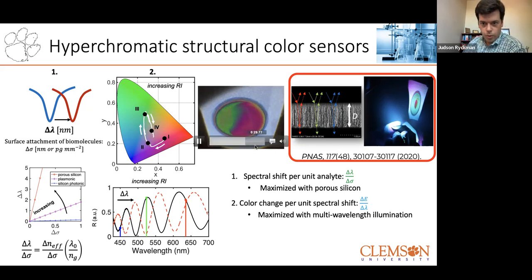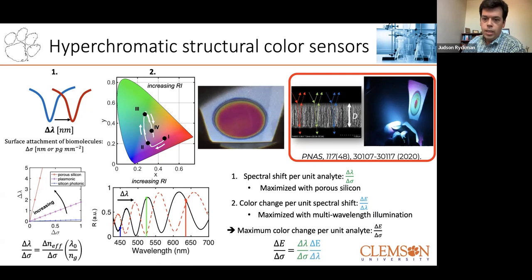This also illustrates one of the nice advantages of colorimetric sensing. It's not just a yes or no type of response, but it's a spatially mapped response as well. And so we actually see the evaporation of the water vapor out of the pores. And this is effectively a very nice structural color effect, where we've combined both the porous silicon and a special illumination strategy. So when we combine those two things, that really allows us to get a maximum color shift per unit analyte. And we've begun doing more sensing type experiments with this.